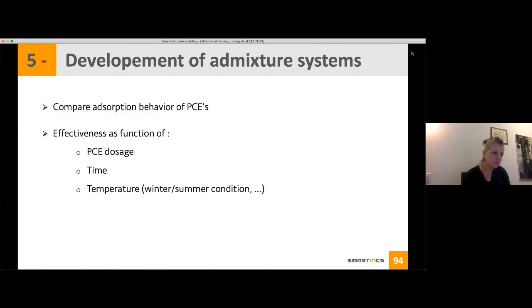What is really interesting, you can also compare the effectiveness with the temperature, and will your PCE react the same with high temperature or low temperature? So then you can see if you do something in December, should you use the same admixture if you are doing concrete in July, for instance? And what is really interesting, you can also see with cement type. I just mentioned also if you have an OPC, and the same class of OPC still in composition can vary, and this can have effect on, let's say, the performance of your PCE.